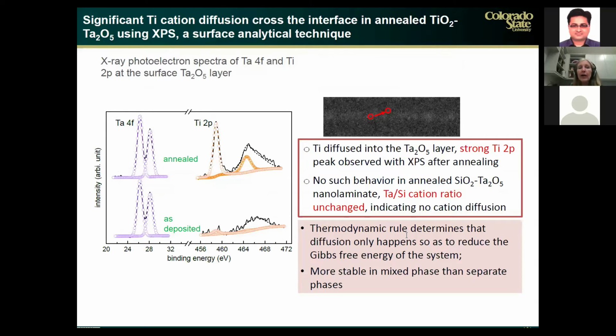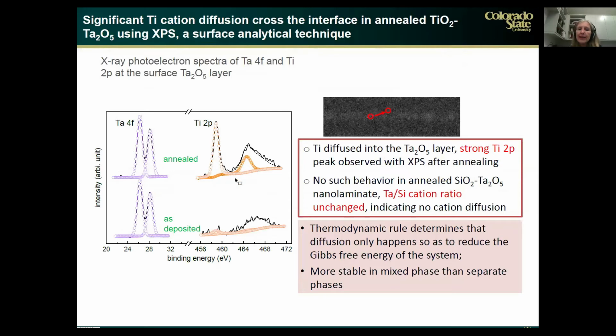We carried out also X-ray photoelectron spectroscopy, and what this data showed us is that, again, in the titania tantala nanolaminate at the surface, when we anneal, we can actually see signatures of titania, which again confirms that there is diffusion of titania into the tantala layer. So what this study has shown us is that in the titania tantala nanolaminate, it is this diffusion, which is thermodynamically allowed and takes place to reduce the total energy of the system, that transforms the material into a morphology that has a lower mechanical loss.